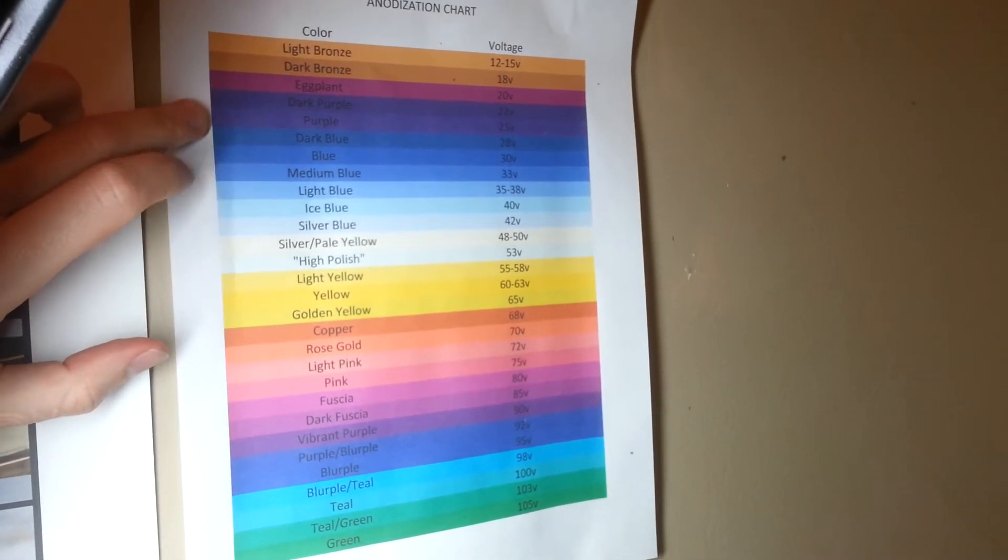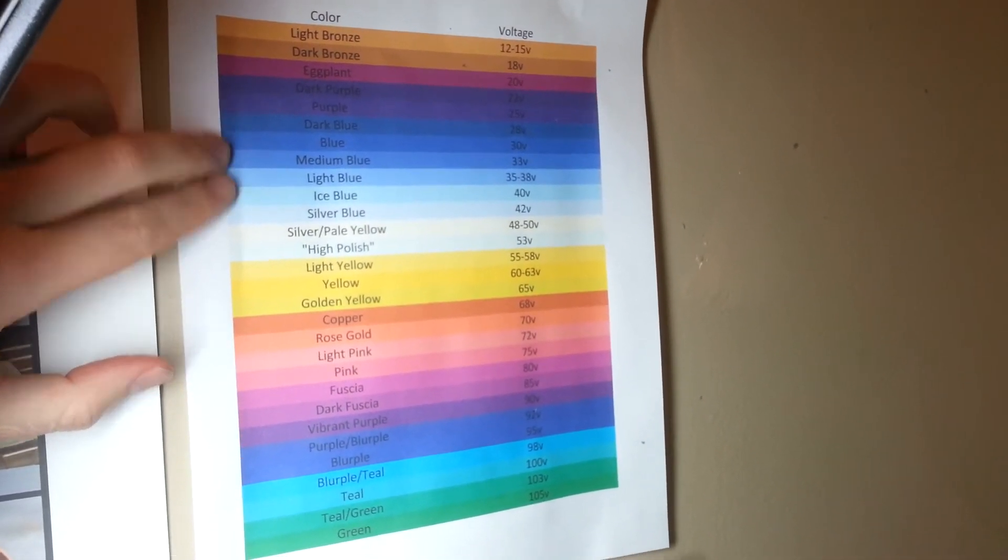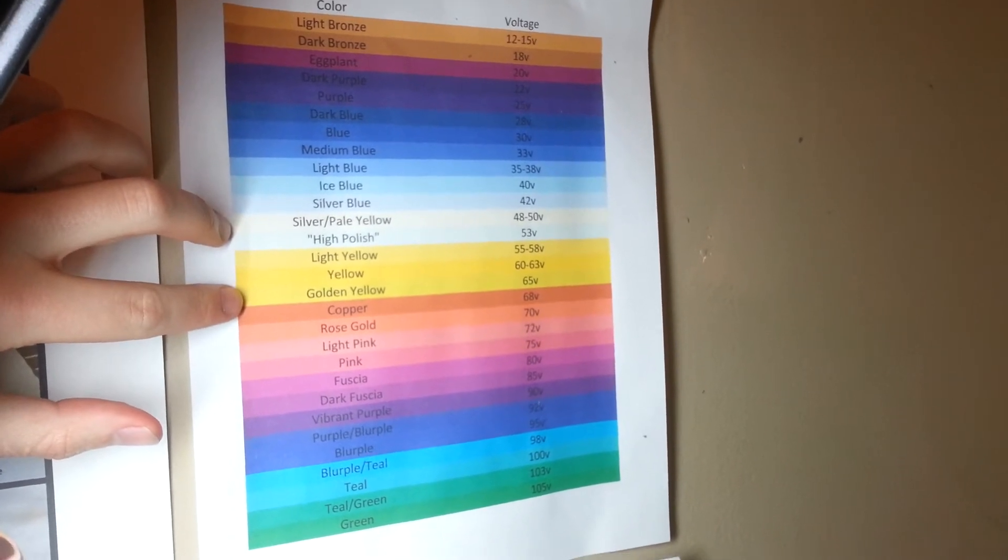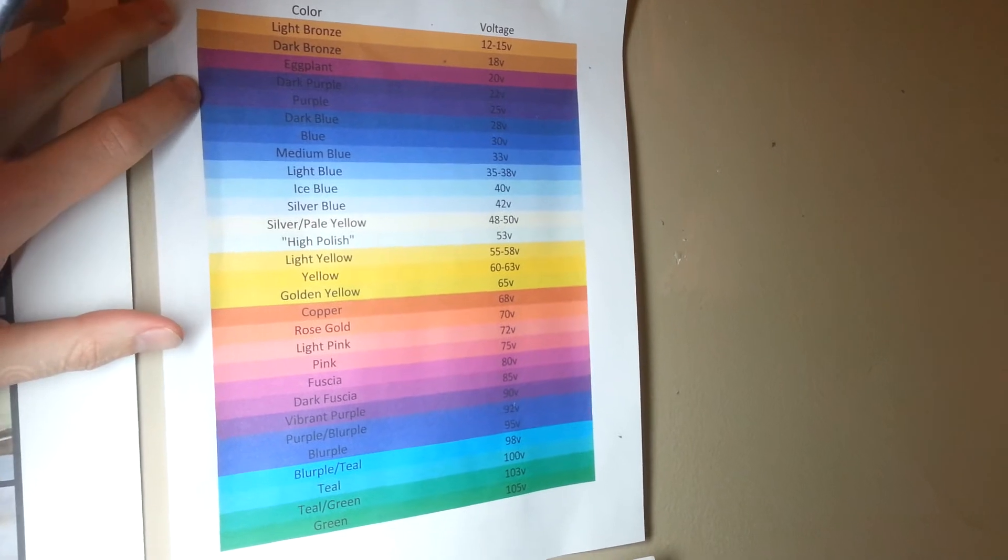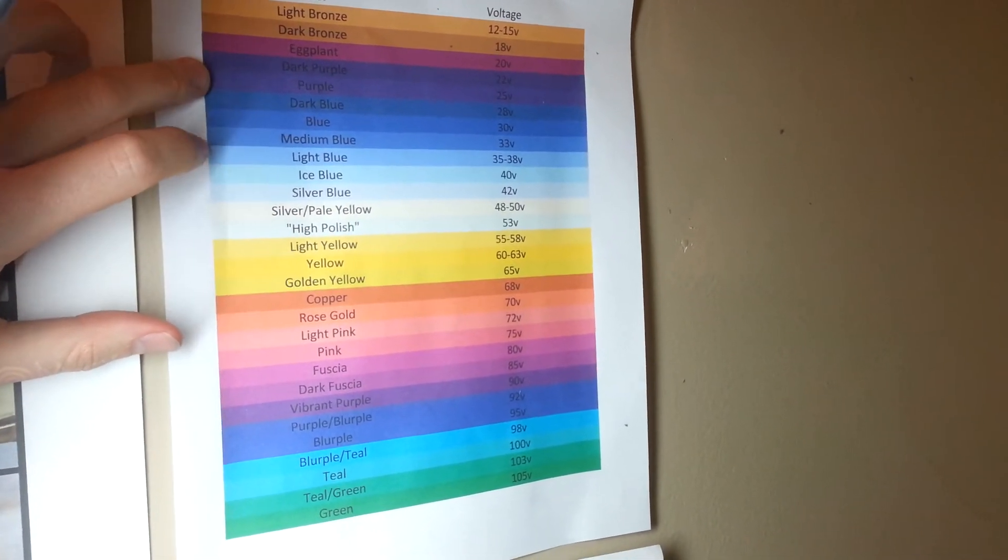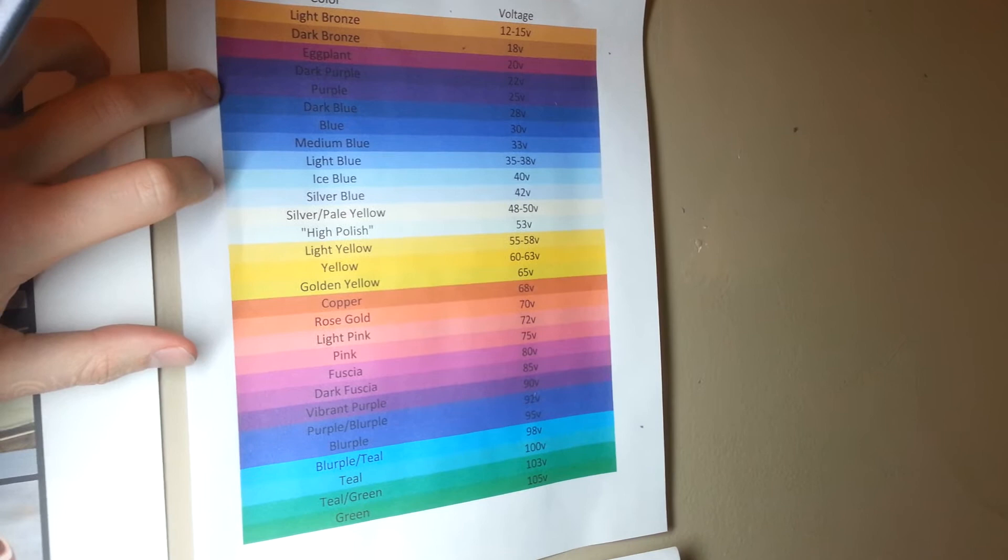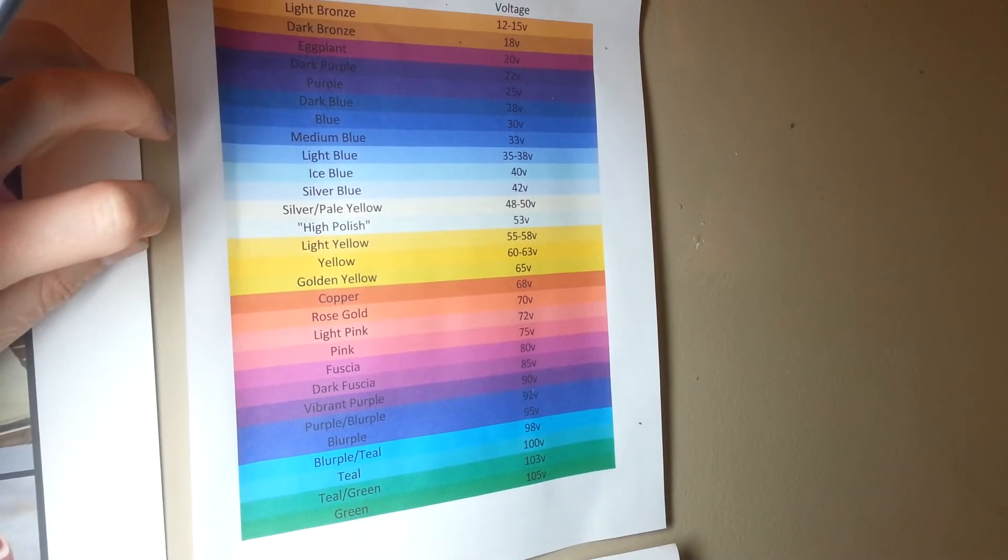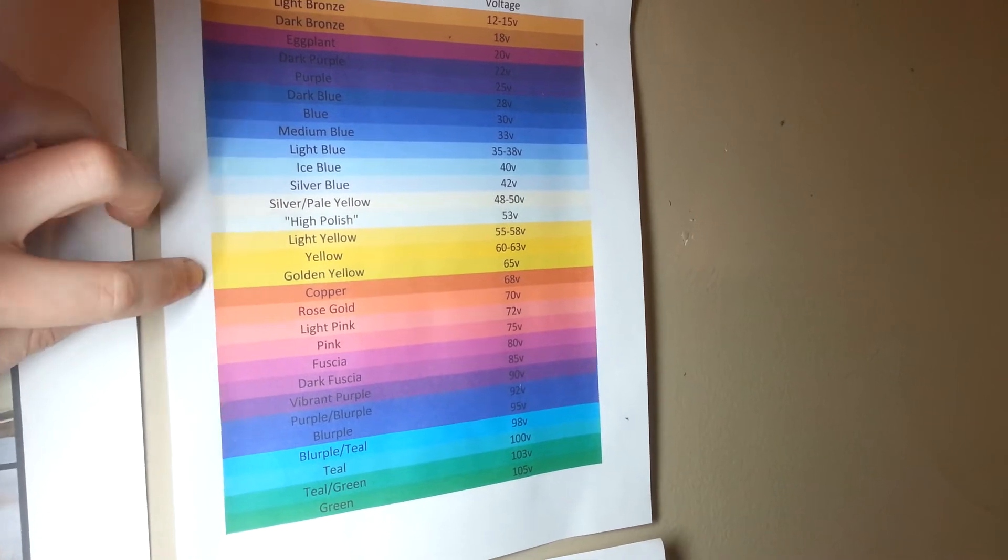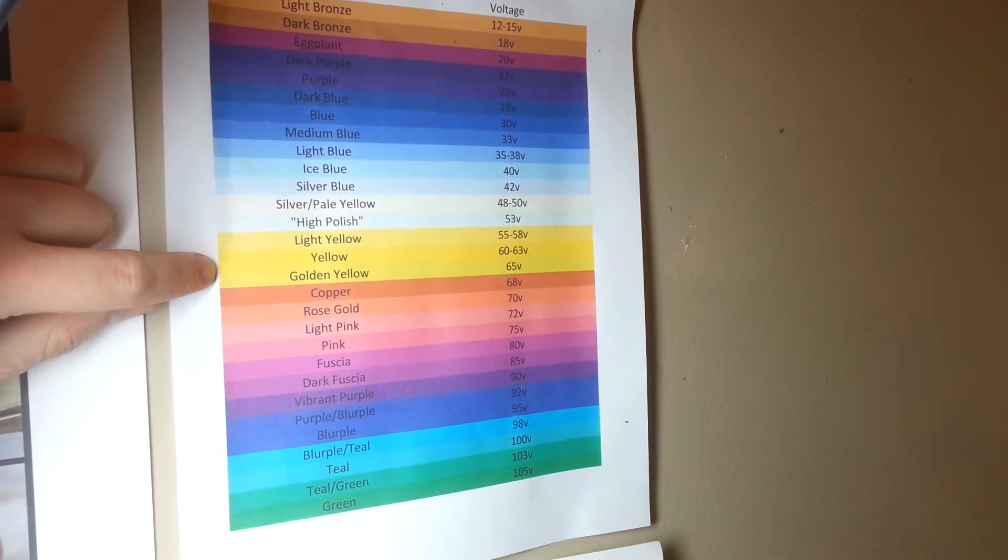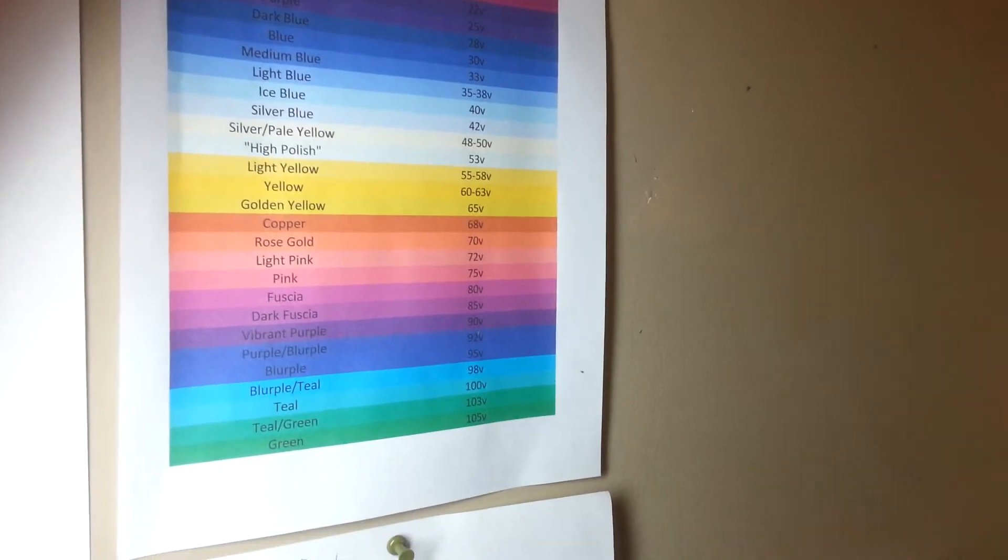since purple is at the very bottom end of our spectrum and yellow is above that, if I were to go through and make the entire piece of jewelry purple and then try to add yellow stripes to it, what would happen is everything would end up turning yellow because yellow is above the purple. So what I'm going to actually start with is we're going to start with doing everything purple. Then I'm going to remove the beads off the piece. I'm going to isolate the parts on the jewelry that I want to stay purple and the parts that are exposed will then turn yellow. I'll show you that in just a second and hopefully it will make a little more sense.